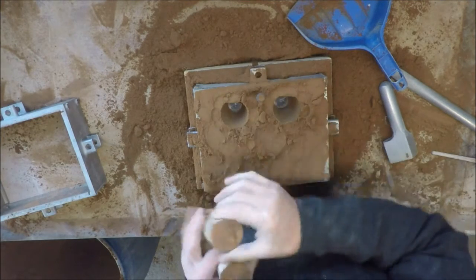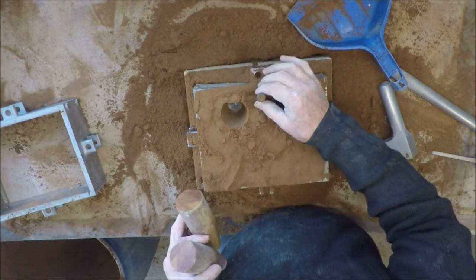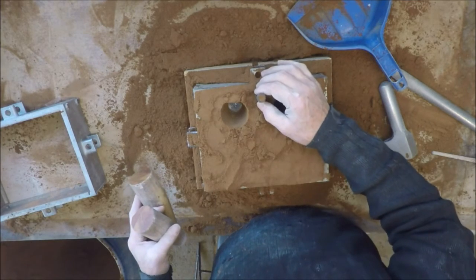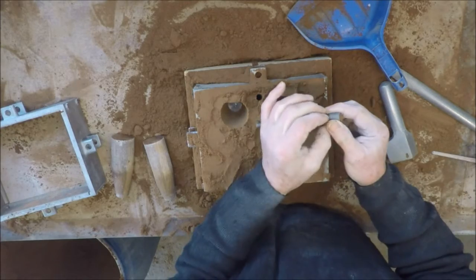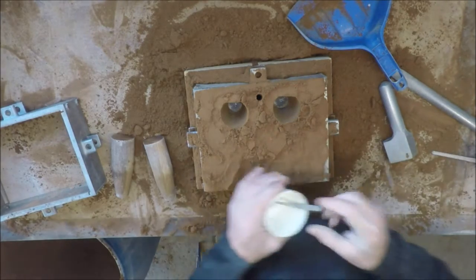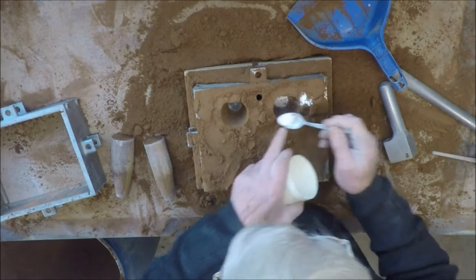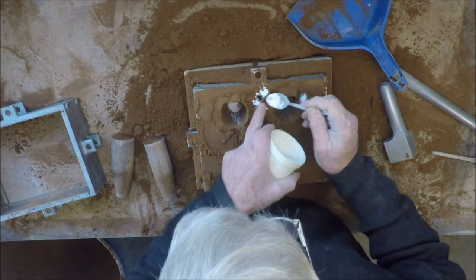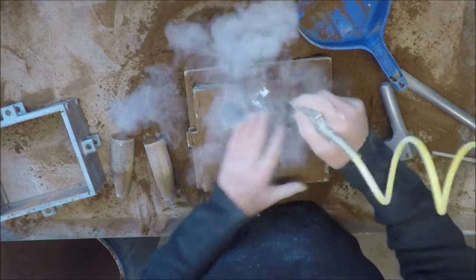Wobble these out. Just twist and pull the sprue pin and wobble out. If you don't, it tends to wobble like that in the mold and you don't wind up with a nice tapered shape in the sprue. You wind up with a sort of an inverted barrel, which is definitely not what you want. A little bit of parting agent down there and blow it around to coat the inside of the sprue and the risers. This just makes it easier to clean out any loose sand later.